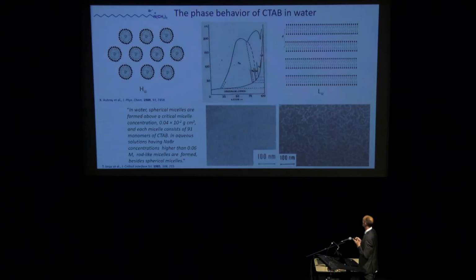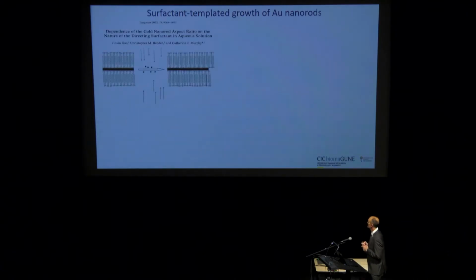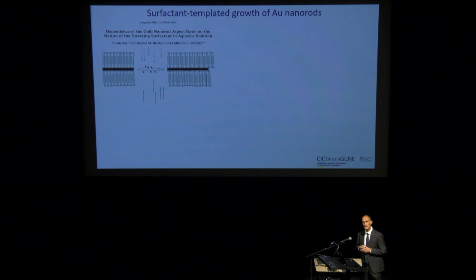And this has been already used by Cathy Murphy in her initial works, talking about a sort of templating effect by the double layer of surfactant, where the atoms would have to be reduced at the tips, and then more surfactant molecules would come and protect the growing particles. This was a bit tricky to understand because the cylindrical micelles typically form at surfactant concentrations which are much higher than the ones we use in the synthesis. And so there were other theories.